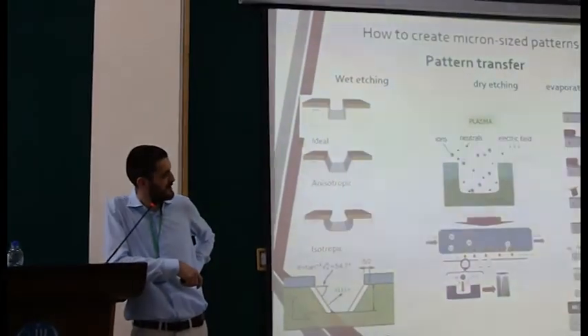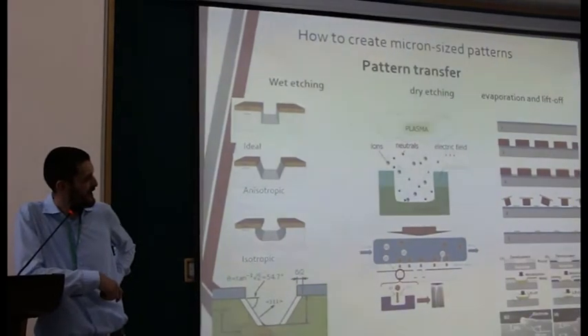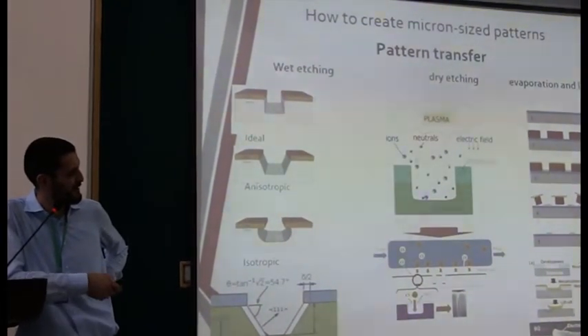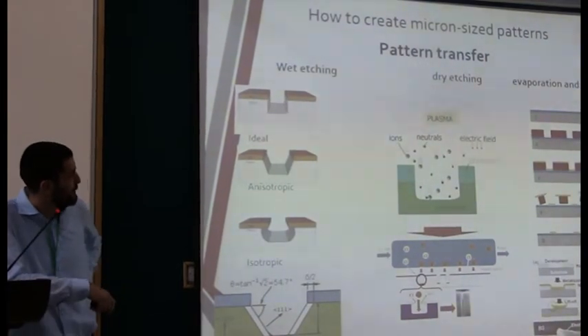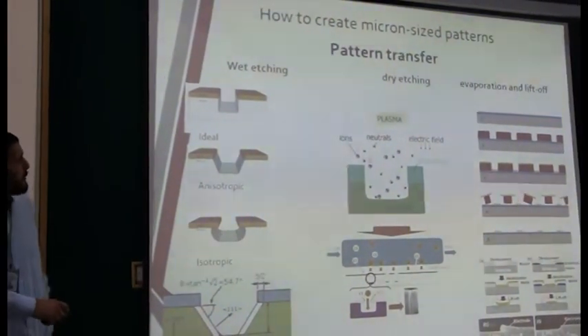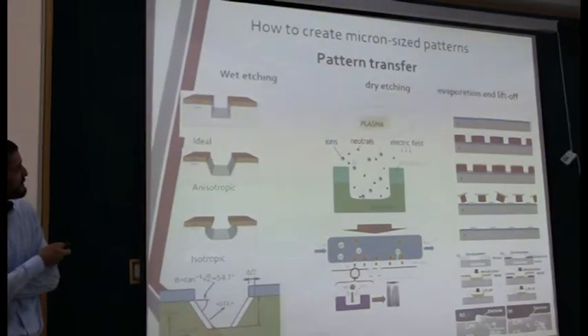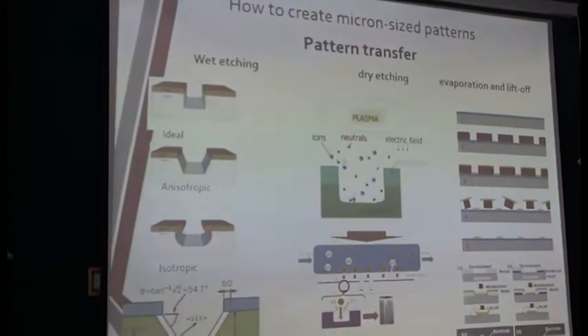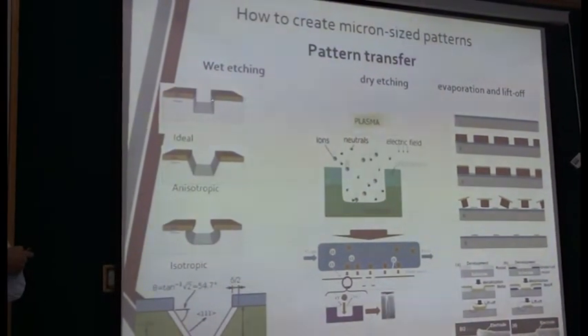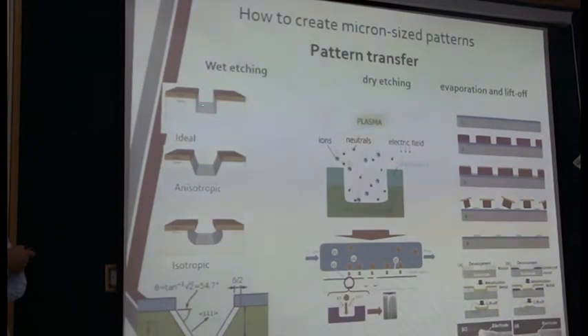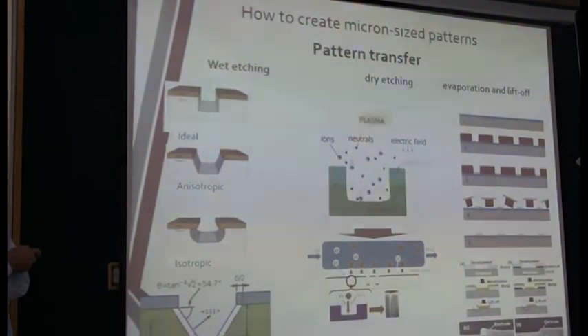And you must combine not just the patterning, but also the post-processing, such as the etching, wet etching, dry etching, or the deposition of particular materials. But you must think also, in this case, what is it that you need to obtain the final sample. Simply, just to describe what we are doing, wet etching. Etching is when you are removing selectively the material on the exposed region of your sample by reproducing the pattern that you have on your resist on the substrate.